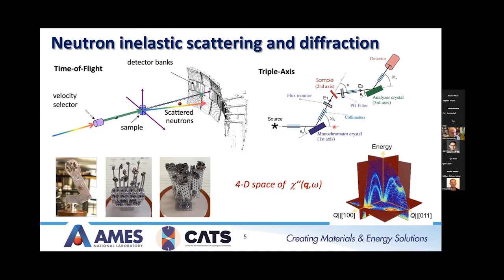So for the triple axis, you just basically select an incoming energy using a monochromator. You hit that on the sample, it scatters off the sample or diffracts off the sample, and then you select the final energy you want to look at using an analyzer, and you can set this up to look at different modes of energy transfer and momentum transfer. So the great thing about neutron scattering, especially magnetic neutron scattering, is you get this overall 4D view of chi double prime, Q, and omega. So the scattering intensity is just related to the imaginary part of the magnetic susceptibility for magnetic scattering.